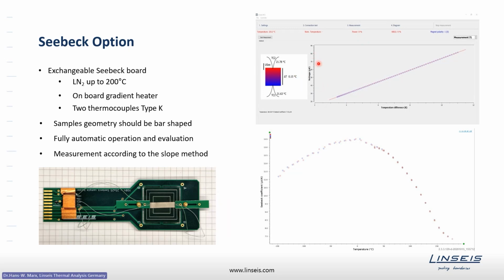And if you do a plot of this thermoelectric voltage over the temperature difference, you get a straight line. And the slope of this straight line is the Seebeck coefficient. And you may perform measurements of the Seebeck coefficient at different temperatures and get a plot, for example, like this. And every dot on this plot was obtained using different temperature gradients, different temperature differences at every mean temperature of the sample.